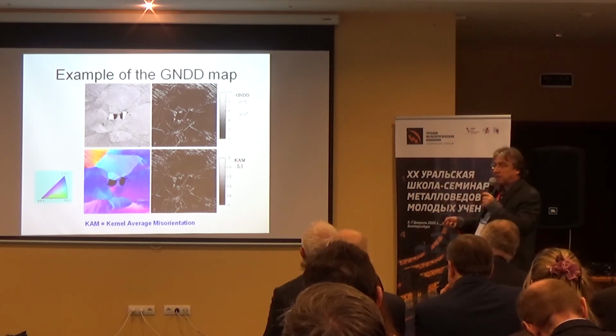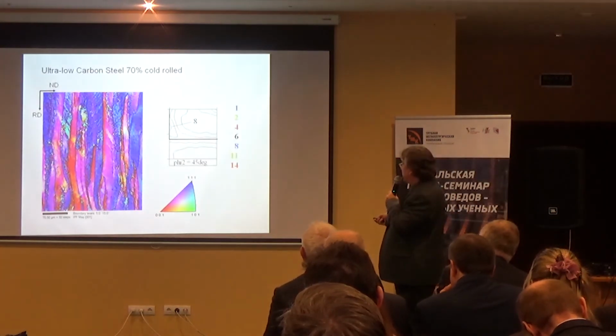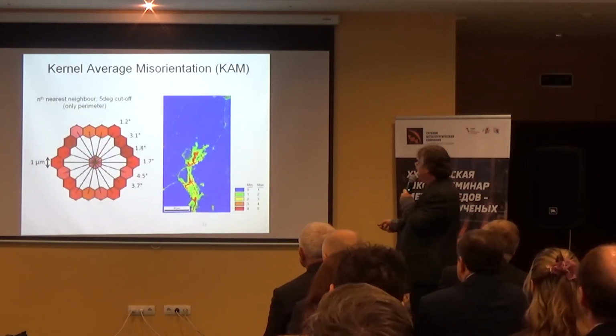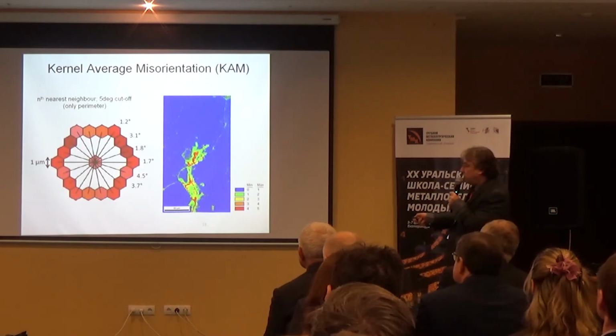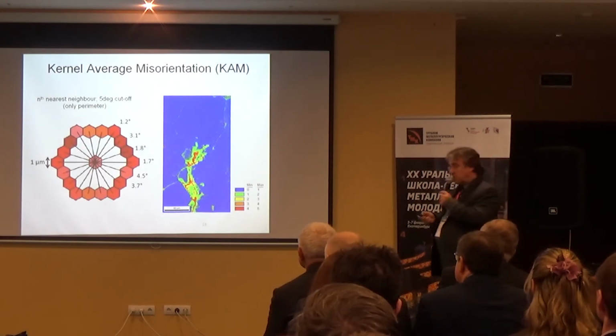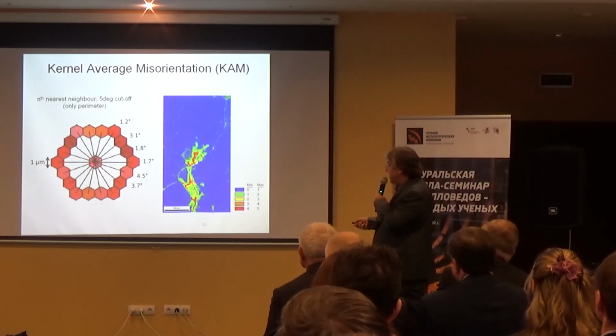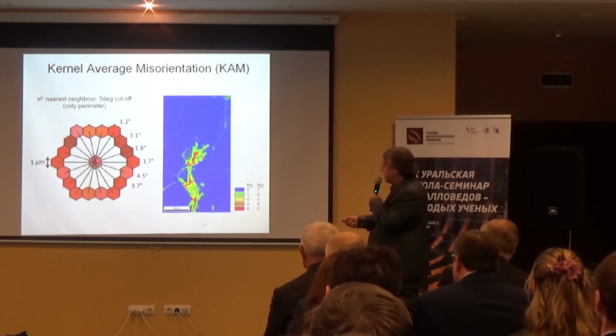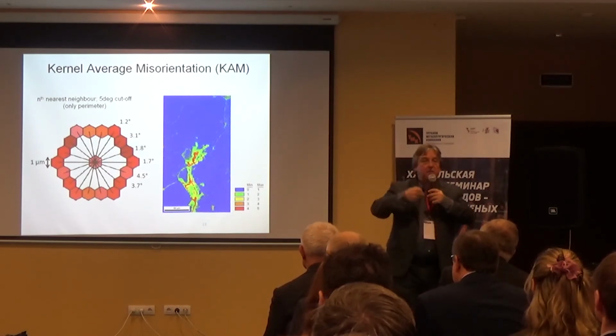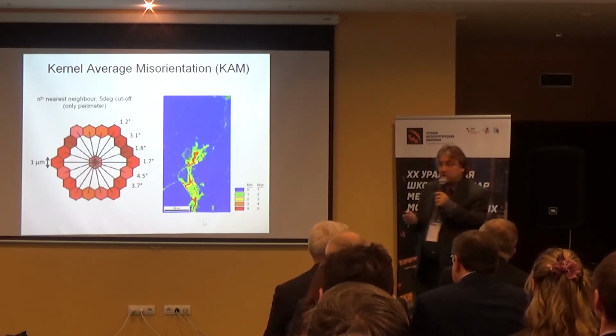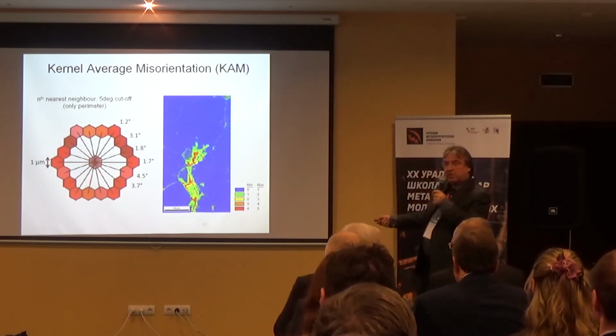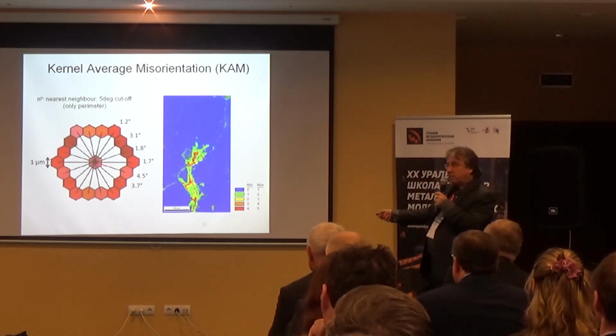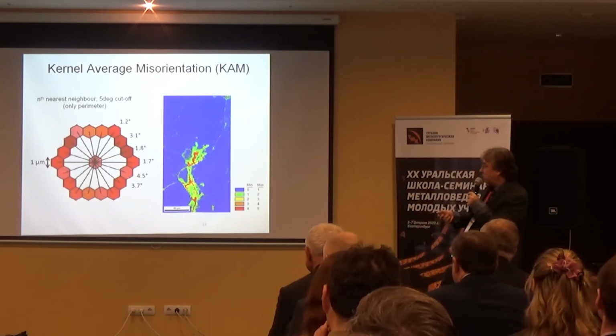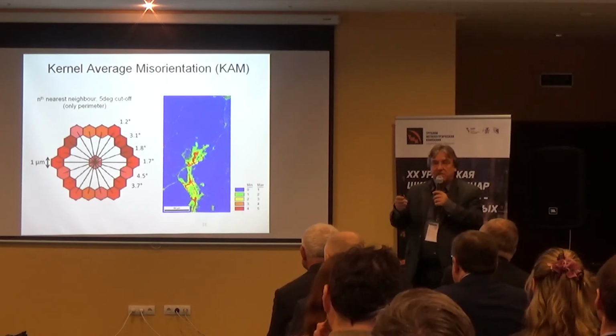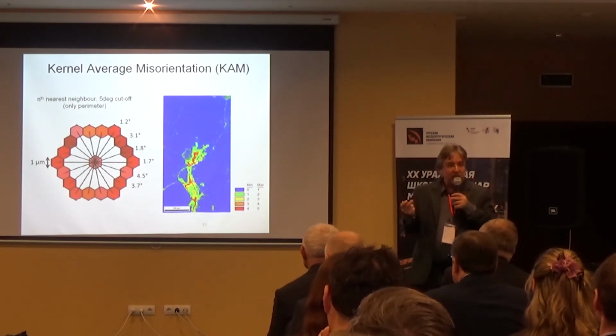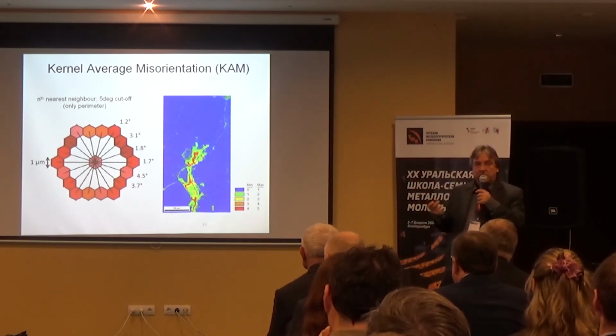What is KAM, or kernel average misorientation? Oh, I thought I had a picture of that. Yeah, here. So if you have an EBSD scan, you measure for each pixel the crystal orientation, and the KAM value is the average misorientation between a certain pixel and a number of neighboring pixels. This can be first neighbor, second neighbor, and so on. So if you make the average between all these misorientations, then you have the average KAM value of the central pixel. So we argue that the lattice curvature that you measure in this way is related to the density of geometrically necessary dislocations.